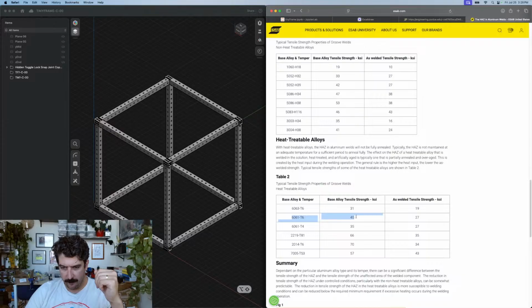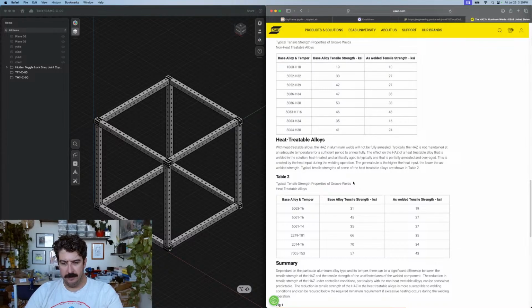6061 T6. They're being liberal here with the value. They're saying 45 KSI, not 38, but the low end is 38. You actually almost half it. So as welded, you go from 45 to 27, which means you just knock down nearly 50% of your yield. And this, ladies and gentlemen, is why you don't want to weld aluminum. Besides the fact it's difficult to do, you lose a lot of your strength.